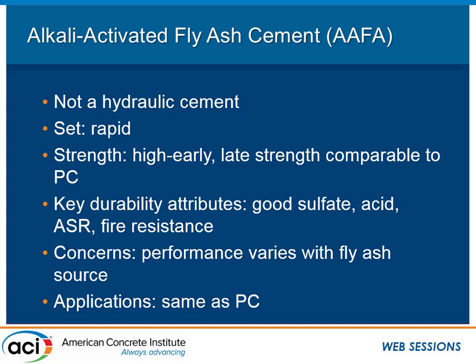So alkali-activated cements are sort of the umbrella category, and then depending on the composition of the material that you're activating, you often hear geopolymers. So if you have a low calcium material such as a Class F ash or glass, you might call that a geopolymer. If you're activating a slag or a Class C ash, you might still just call that an alkali-activated cement. But these are not hydraulic cements, and can have a rapid set. As we all know, probably, when you're looking at high volumes of fly ash or slag or glass, the composition of that material has a super big impact on performance. So if you have a Class F ash or a Class C ash, obviously you're going to get a whole different material.